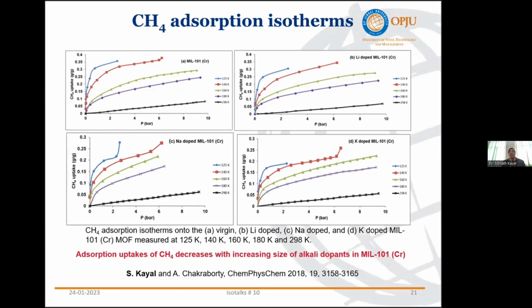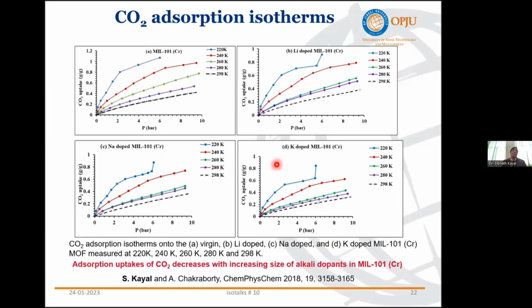And this is for the carbon dioxide adsorption behavior. The same features as the methane adsorption: for this MIL-101 and its alkali dopants, what are the adsorption characteristic features? This figure shows the same features you can observe. Point number 1, the adsorption capacity decreases with increase in temperature. Point number 2, the adsorption capacity increases with increase in pressure. And point number 3, the adsorption capacity decreases with increase in alkali ion dopant. The same observation we have found, and it is quite obvious.